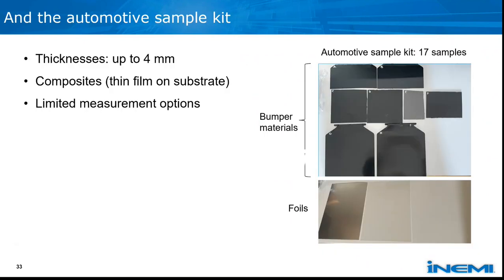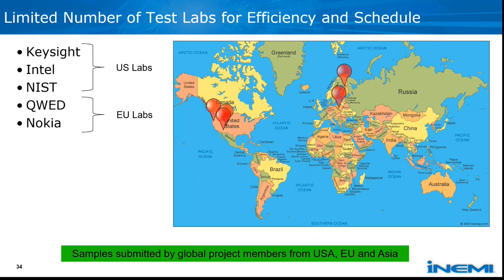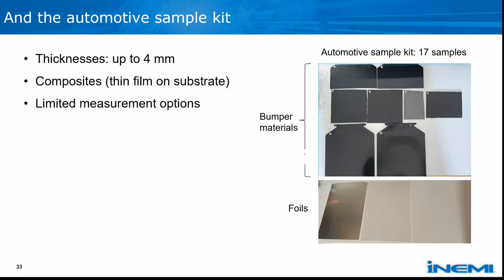Additionally, we had the automotive sample kit, which added a lot of kind of challenges that we couldn't extract from the electronics materials. And so shown here on the right is just photos sort of the two clusters of automotive samples we had submitted. So on the top are these sort of bumper materials that were up to about 4 millimeters thick, which is obviously way thicker than our typical electronics materials, and added some measurement challenges. And on the bottom, we had some of these foils, which were substrates, some of which had thin films on top of them. So those were between 100 microns and about 600 microns all told.